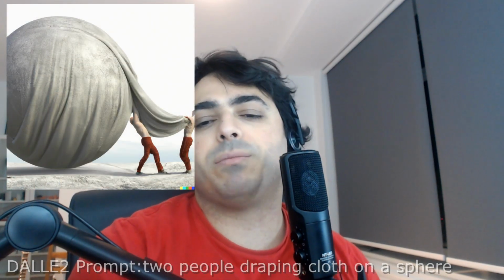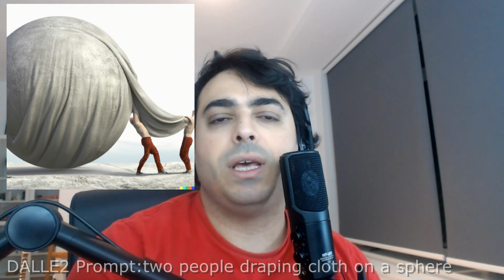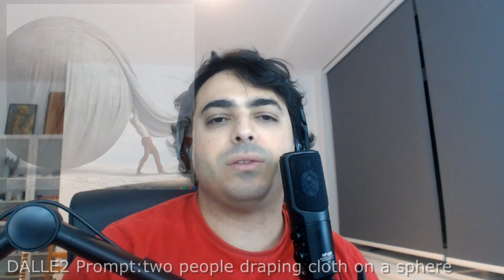That's usually done by having a mold, a positive shaped mold, just an embossed surface where you place the cloth, you place the weave of fibers, and you shape it to the shape of the mold, and then you infuse later, you add in the adhesive. This process of shaping the layers onto the mold is called draping. And even draping is a process that was developed from the cloth industry, when you have a mannequin and you start draping the cloth on the mannequin to fit the shape of the person you're designing the clothes for. This was adapted for the composites industry to also take the shape of the blade, and you drape the fiber mesh on the mannequin of the blade, and then you add in the adhesive to keep it in a fixed shape at the end, so it becomes a solid body, a solid composite.